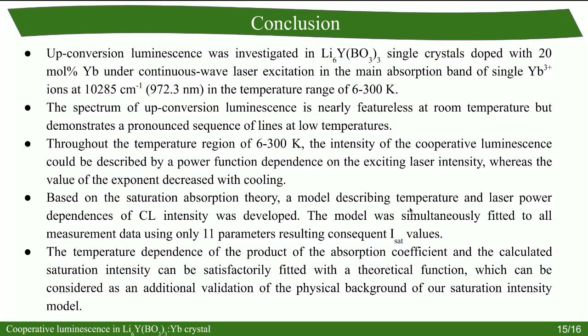Based on the saturation absorption theory, a model describing temperature and laser power dependencies of cooperative luminescence intensity was developed, and the model was simultaneously fitted to all measurement data using only 11 parameters, resulting in consequent saturation intensity values. And also the temperature dependence of the product of the absorption coefficient and the calculated saturation intensity can be satisfactorily fitted with a theoretical function, which can be considered as an additional validation of the physical background of our saturation intensity model.